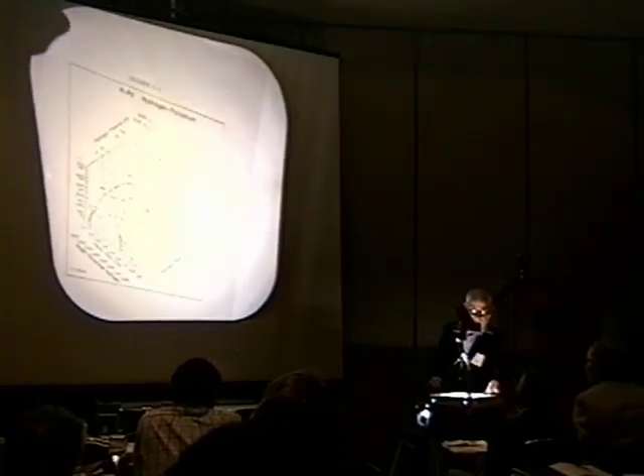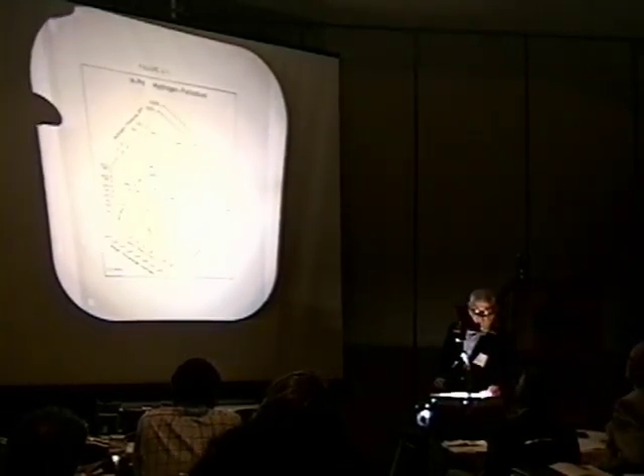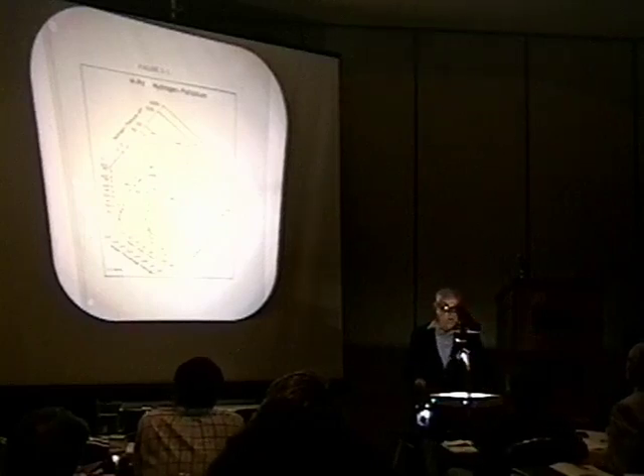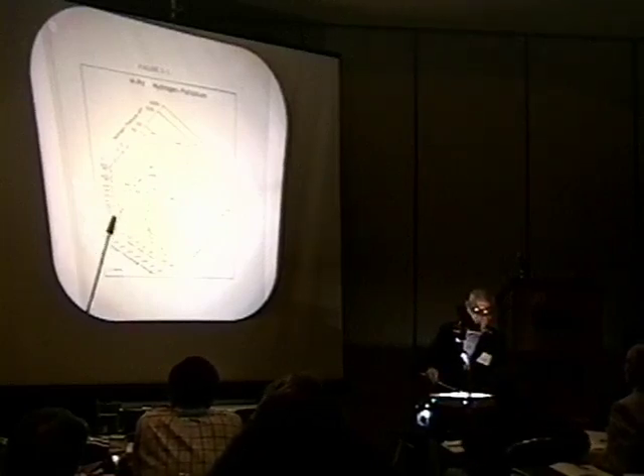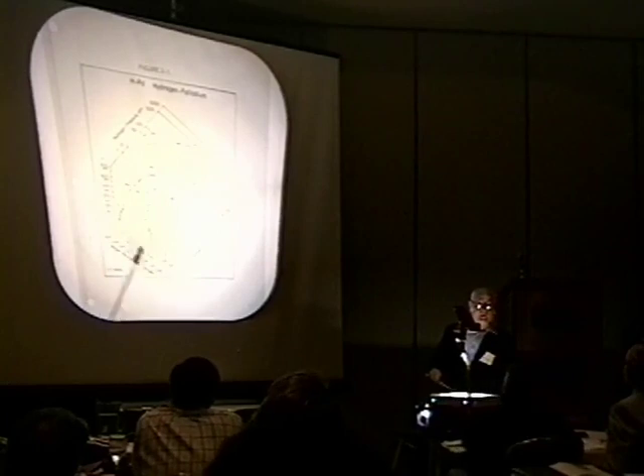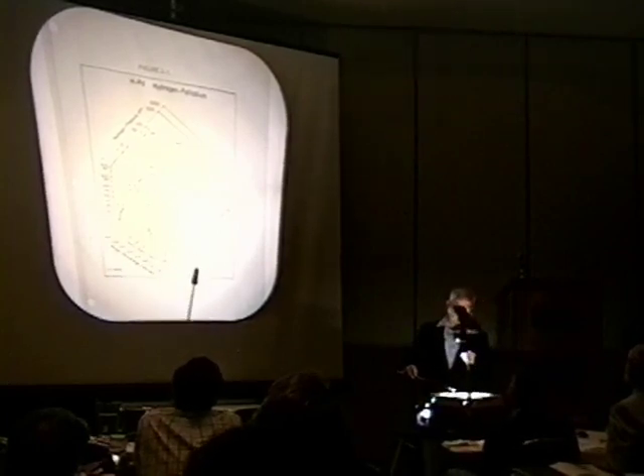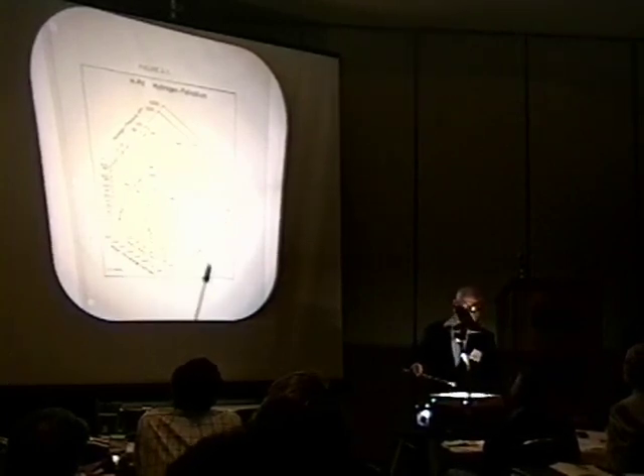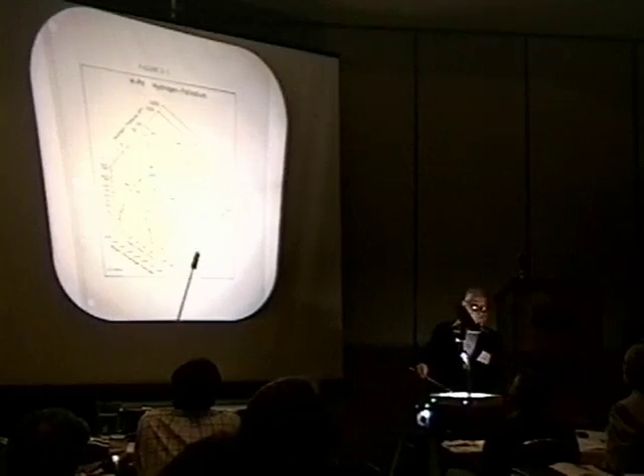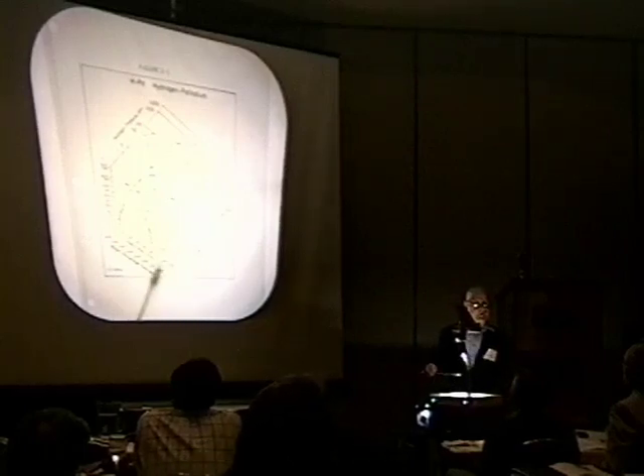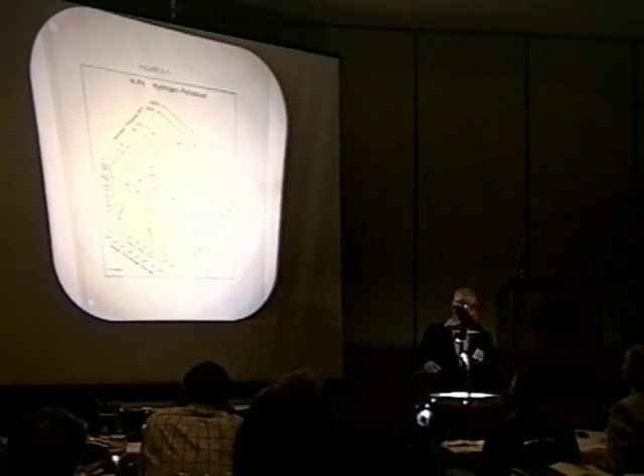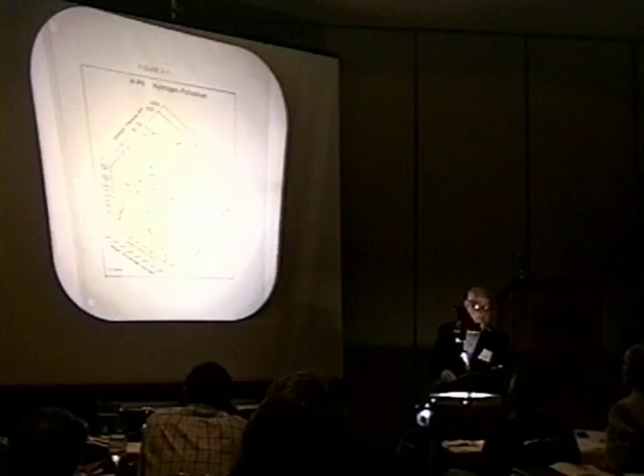And this particular diagram comes from the American Society for Metals, published during the 70s. And here we are, T, C, P: T, temperature, C, concentration, in terms of H over Pd. And in this case, instead of chemical potential, the scale is hydrogen pressure. And this scale is constructed for gas loading rather than electrolytic loading. But the scale could just as easily be the electrode potential for electrolysis.